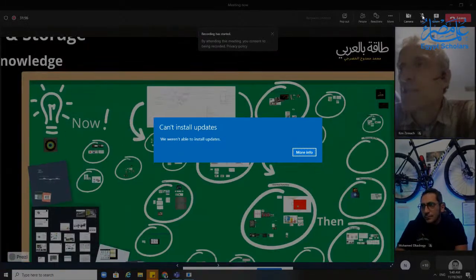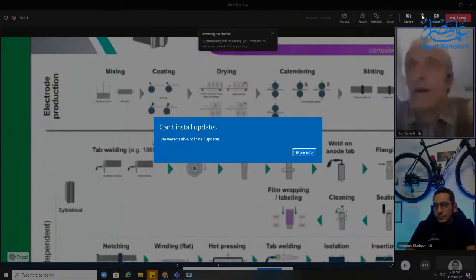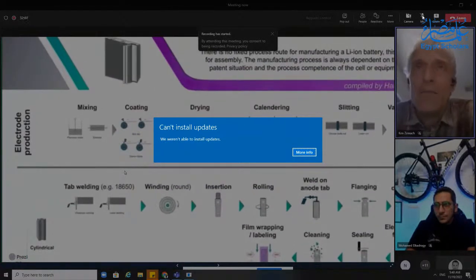You got to make that graphite layer, which is coated on aluminum. I'm sorry, I got it wrong, which is an anode. So it's coated on copper because it's the anode. And then you've got this cathode material, which is coated on aluminum. So let's go to mixing. So the first thing that you do, and remember, let's take a basic anode. I said that the anode is graphite, a conductive agent. You're talking very little bit of conductive, 0.5% by weight, 1% by weight, maybe 2%.